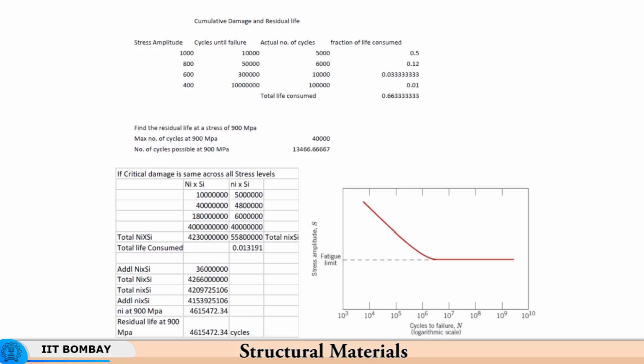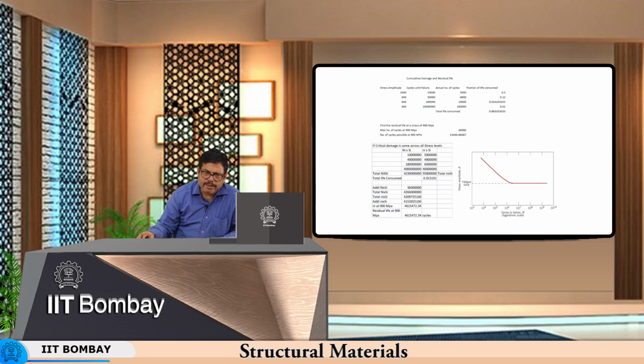The ductility gets exhausted, then the crack gets nucleated and propagates throughout the entire mass of material. Whereas here you are in the elastic regime, so there is no permanent deformation. What is happening here is that there is only a change in the sign, a change in the direction of deformation, in case you have both tensile as well as compressive stresses. And so, we have a fatigue limit which is much lower than the yield point of the material.